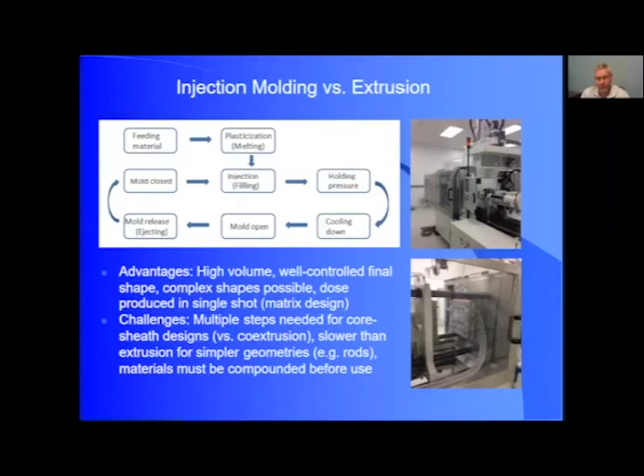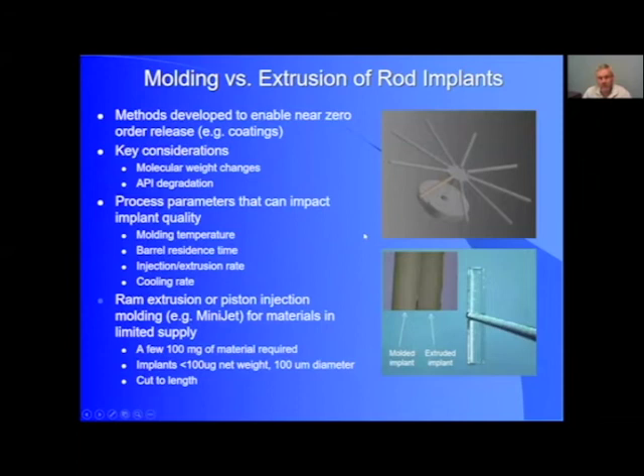It still can be slower than extrusion for simple geometries such as extruded rods, which are cut to final length. And the materials must be typically compounded before pelletized and used as feedstock for the injection molding process. Whereas in some cases with a hot melt extrusion, with a twin screw extruder, you can mold and extrude in a single pass. So comparing molding versus extrusion of something like a rod implant, you can do it by molding, but if you wanted, again, to make a core sheath design, you're going to possibly have to do something different, such as a coating over the surface of the molded implant.